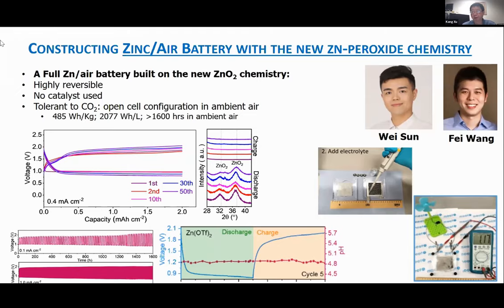However, for the cathode side, we can assemble the cell in a very easy way. We show in that paper, with a video, just a simple air cathode material, porous carbon, pouring electrolyte. You can assemble the cell, which can work in the open air because there's no pH change. As shown here, pH is almost constant. So it's tolerant against the carbon dioxide in the atmosphere. So it's not a zinc oxygen cell, it's a real zinc air cell. So far we can achieve up to 800 cycles at 2C, that's 1600 hours.